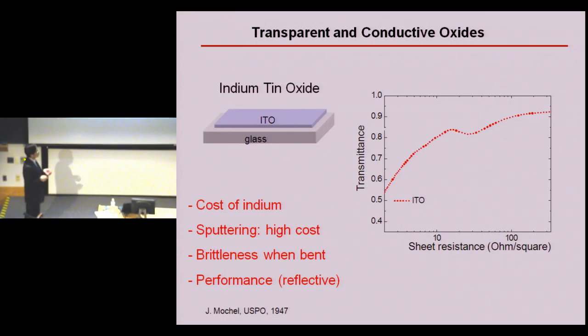So this is a thin film deposited on a glass substrate. And this material has been used for many years. But meanwhile, this material has many, many problems. One is that indium is an expensive material. And also, the process to make this kind of structure is a vacuum-based process. So that means also high cost. And meanwhile, essentially, this material is a ceramic material. So when you bend the material, this material will break. And this is not good for flexible electronic applications.